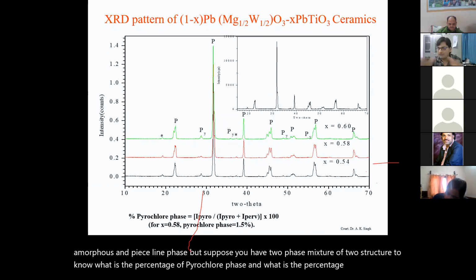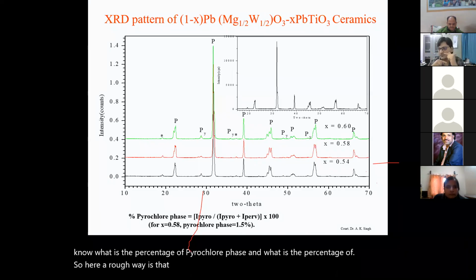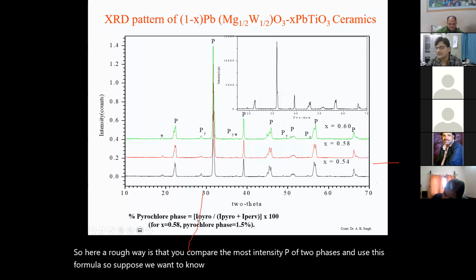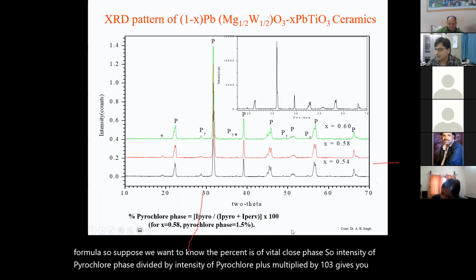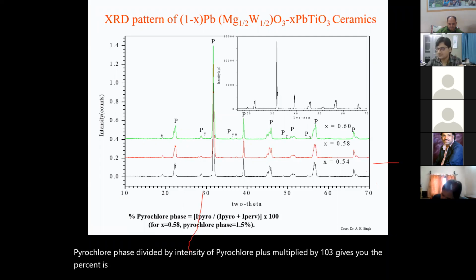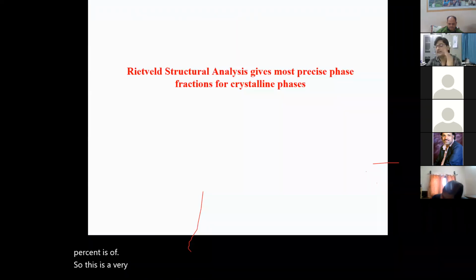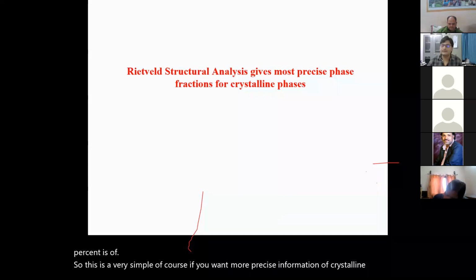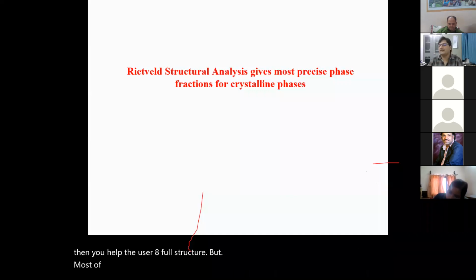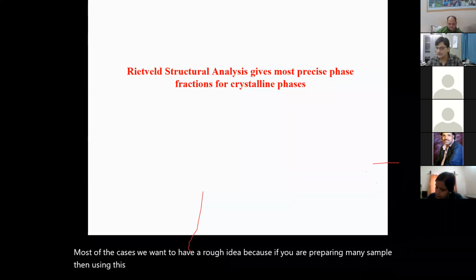So here a rough way is that you compare the highest intensity peak of the 2 phases and use this formula. So suppose we want to know the percentage of pyrochlore phase. So intensity of pyrochlore phase divided by intensity of pyrochlore plus perovskite, multiplied by 100. This will give you the percentage of pyrochlore phase. So this is a very simple way. Of course, if you want more precise information on the crystalline phase, then you have to use Rietveld structure analysis. But in most cases, we want to have a rough idea, because if you are preparing many samples, then using this rough idea, you can report your result.